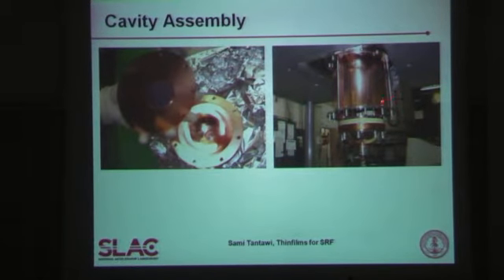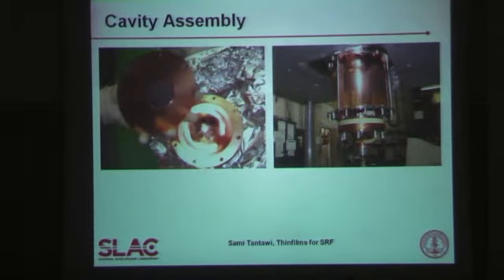Essentially, it's put on a pulse tube that cools it down from room temperature to about 3.5 Kelvin in about an hour or so. And we change the sample from room temperature to vacuum. The whole process takes about 3 hours at most to go to about 3 Kelvin from the sample being in your hands. The system has its own roughing pump. Everything is self-contained in one single structure. And what you see here is the body of the cavity. This body of the cavity gets inserted into the pulse tube, and the head of the pulse tube is here, and the sample lies around here. This is the cavity itself, and this is the cover of the cavity that contains the sample. And the sample is directly touching the head of the pulse tube.